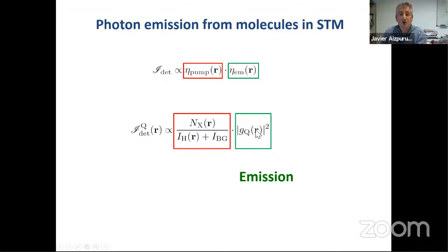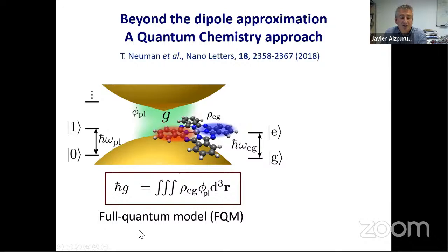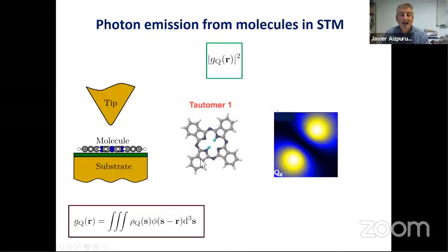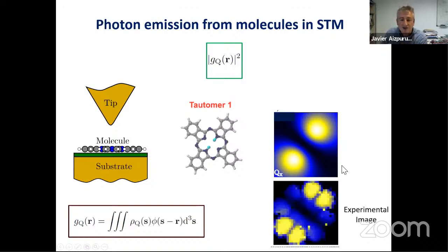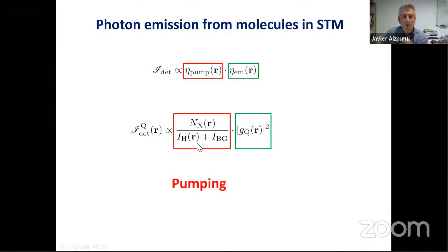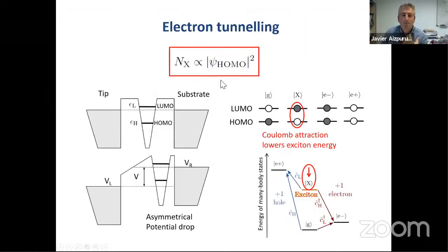So we need to calculate G, but I showed you just a second ago how to calculate G. G is this integral in space of the plasmonic inhomogeneous field multiplied by the spatial distribution of the transition. And when you do that for this tautomer, you calculate the transition with quantum chemistry methods, you calculate G squared, and one obtains this map of the pico cavity emission. It's a dipolar emission with the hydrogens like this. And this is the theoretical dipolar map of the coupling strength. But remember, the experimental image looks like this. They don't look equal to each other. Here on top, we address the emission properties, but not the excitation. And we saw that for the total emission, we also need to account for how we excite the exciton, right? The pumping. So we need to do a transport calculation to see the population of this molecule.